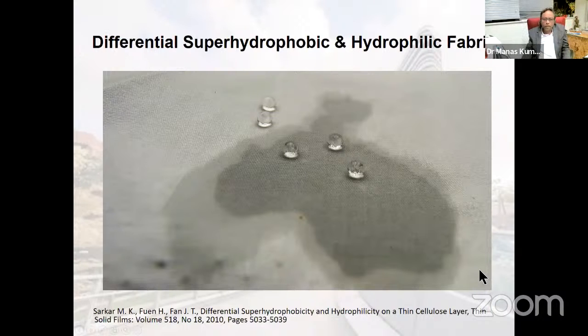So this is another kind of material we developed. Here you can see the water is rolling on the outer surface, but the inner surface is wet. So it's a differential super hydrophilic and hydrophobic fabric. On the outer surface, you can see the water is rolling, and the inner surface is already wet, which is quite visible. And these kinds of materials are very suitable for band-aids, such kind of things.